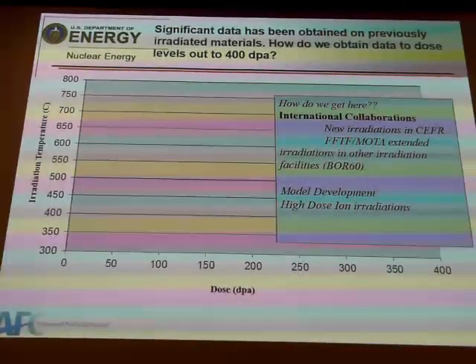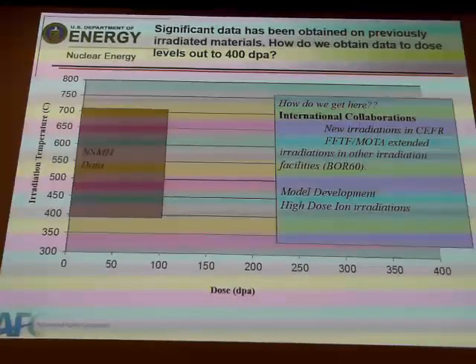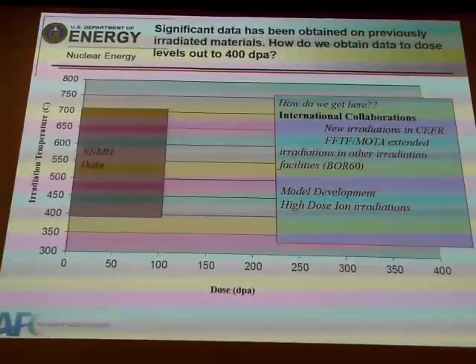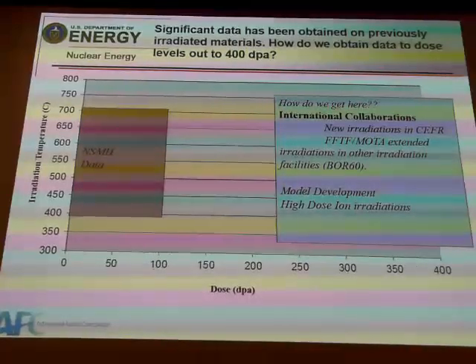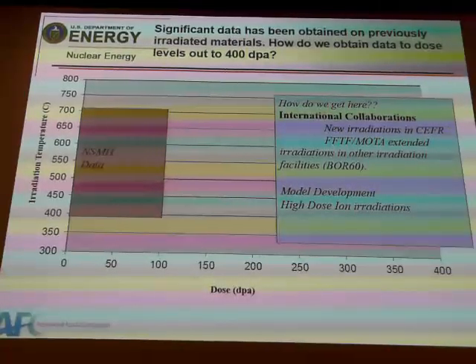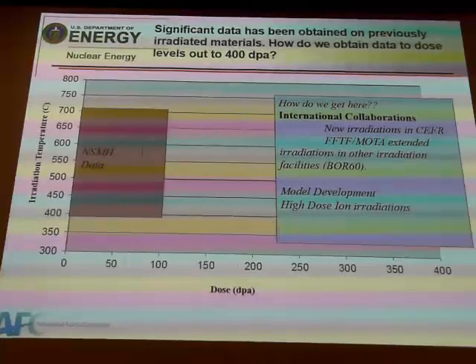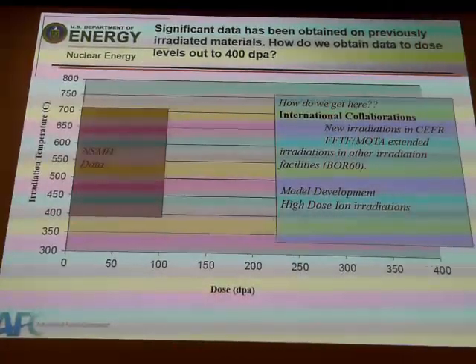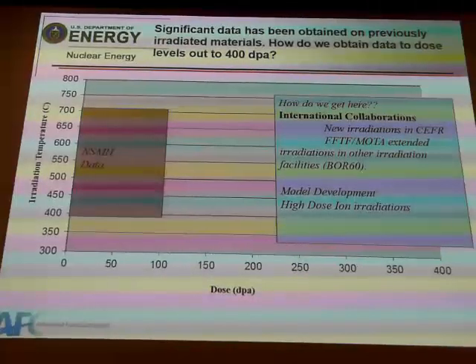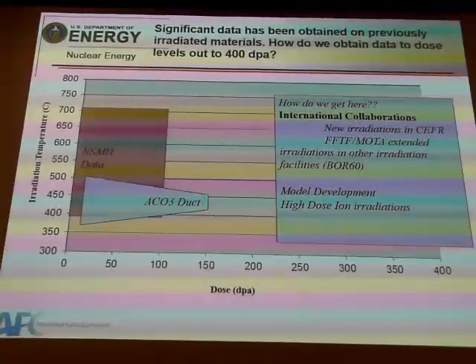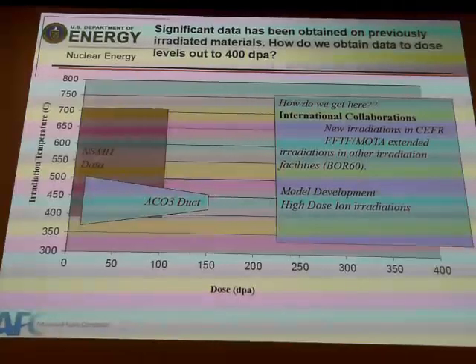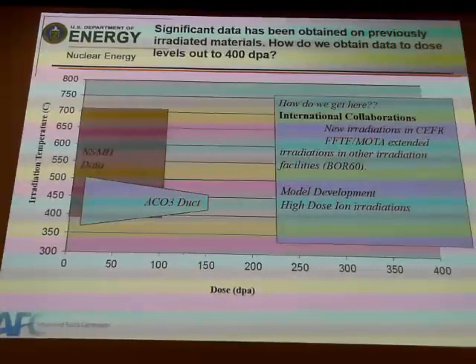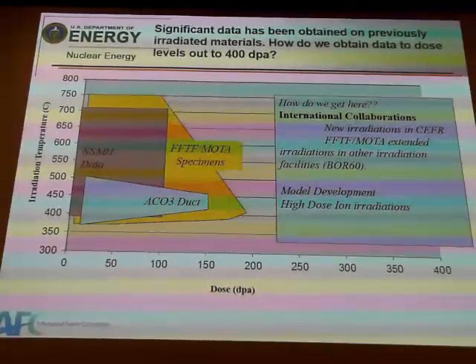So how do we get this data? There's significant data that we're trying to pull together to understand what the better materials are after radiation to high dose at specific irradiation temperatures. This is the Nuclear Systems Materials Handbook, which has significant data mainly on austenitic stainless steels out to about 100 DPA. This is some data that we recently got from this program, the ACO3 duct, where we received the material from the Fast Flux Test Facility and got data on an actual component out to 155 DPA.